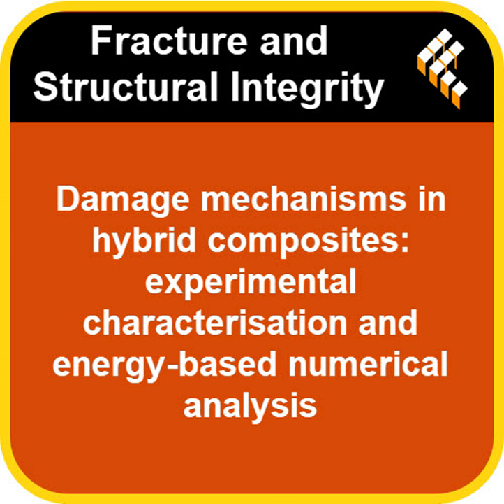Critically, they kept a close eye on the amount of kinetic energy in the model. Why kinetic energy? If that energy stayed really low, like below a small percentage of the internal energy, it meant the process was behaving in a slow, controlled way, quasi-static, as they call it, just like their experiments. Gotcha. Plus, as we touched on earlier, they initially used their experimental data to get good starting values for their damage models, and then tweaked them, optimized them, to get the best possible match between the real and virtual tests.